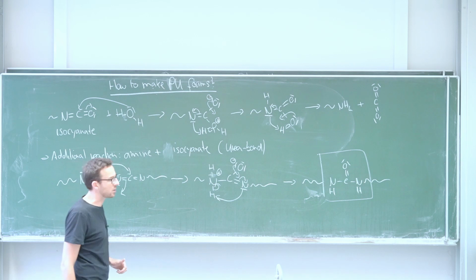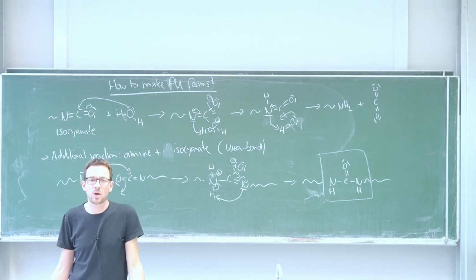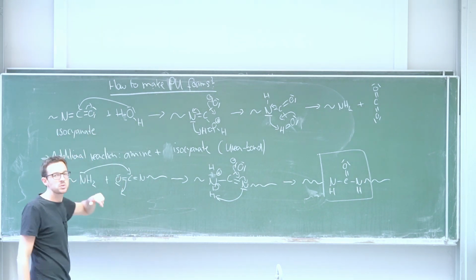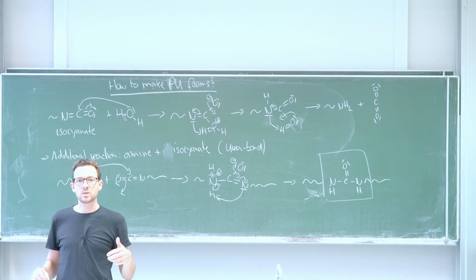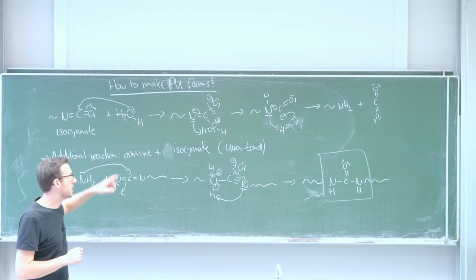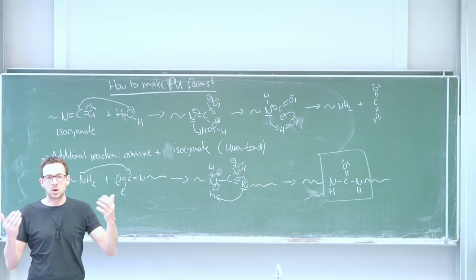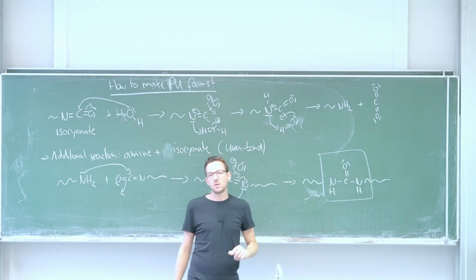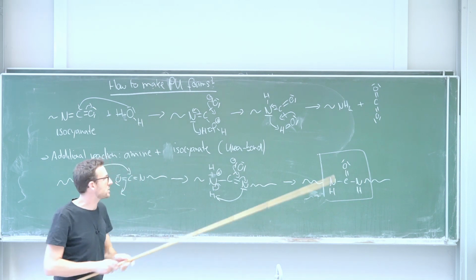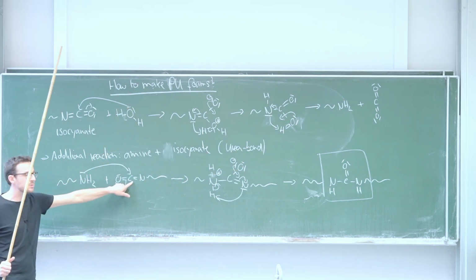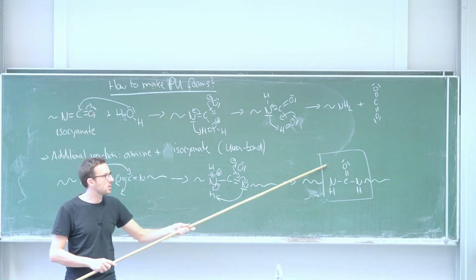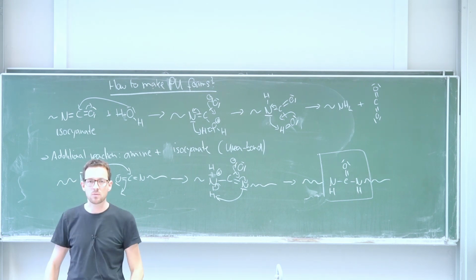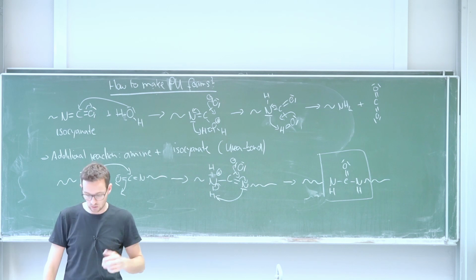So you see, again, to make this foam, you actually have three things that are important. You need to make a pre-polymer that contains these isocyanate groups at the outside, and you will see in a second. You do this by adding a bit of an excess of the isocyanate in the first reaction. So this comes out of the bottle, takes up water, converts into an amine and CO2, so it starts to foam up. Meanwhile, this amine continues to react with more polymer that comes out of the bottle and forms a urea bond, which hardens the material even further because the polymers become longer. And this is how you make this very stiff construction foam or insulating foam.